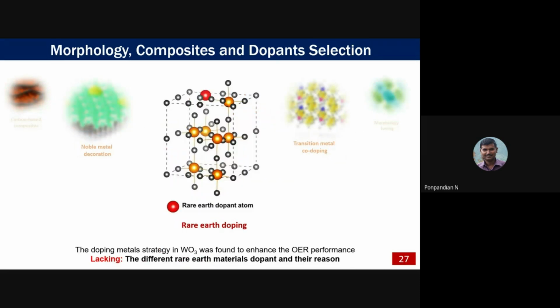Now you can see here, in the tungsten oxide, the next step, we are making a different type of composite. Here, in addition to the tungsten oxide, we are adding or doping some rare earth elements, that is europium, cerium, gadolinium, and this kind of rare earth element we are adding to the tungsten oxide. In that way also we can tune the band gap of the tungsten oxide, and improve the efficiency of that particular material.